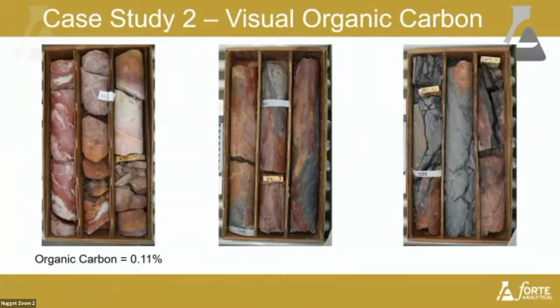So knowing that one, and assuming the dark marbling in the middle one is going to be higher organic carbon, right? You would assume it would be much higher visually. Looking at the second one, it's actually going to be 0.16%. So visually it seems a lot more, but both are considered above the amount of organic carbon that would be potentially preg robbing. Cool. That's about right.